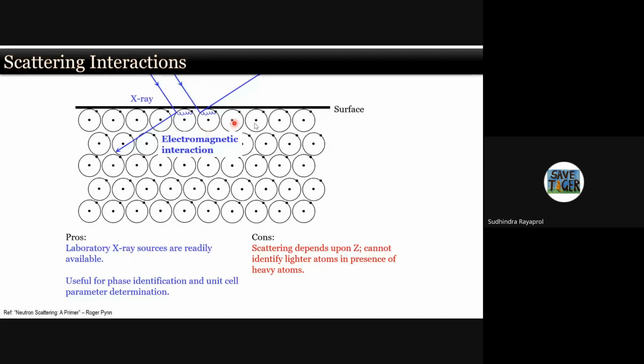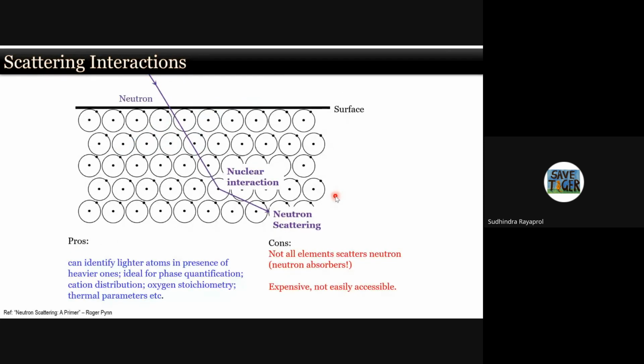Of course, the problem with X-ray diffraction is that it depends upon the number of electrons present in your sample. So it is strongly Z dependent, because the more electrons you have, the stronger the electron cloud, and the more scattering there will be, right? Which is not the case with neutrons. Neutrons being chargeless, they can penetrate deep into the sample, and can interact with the nucleus of the atoms present in your sample, and because of this nuclear interaction can get scattered, right? So the advantage is that it is not Z dependent, unlike X-rays. Therefore you can identify lighter elements in the presence of heavier ones. You can do phase quantification, you can determine the cation distribution, oxygen stoichiometry, thermal parameters, and so on.